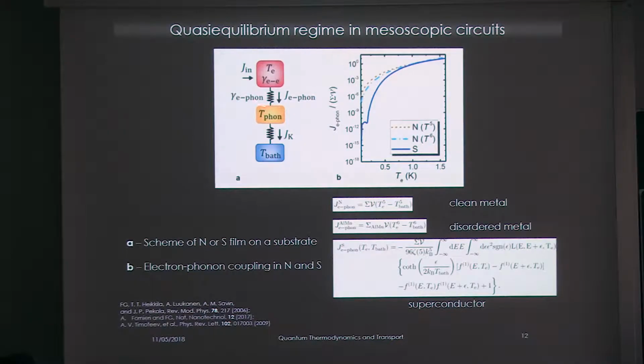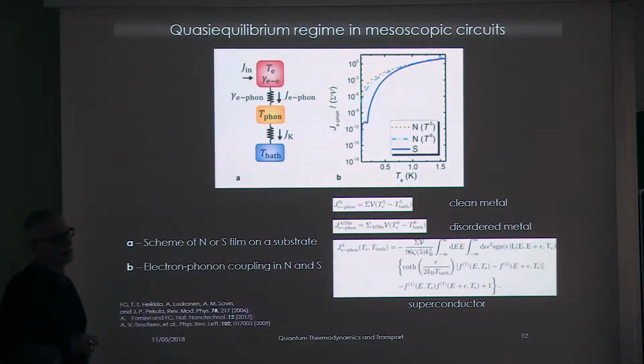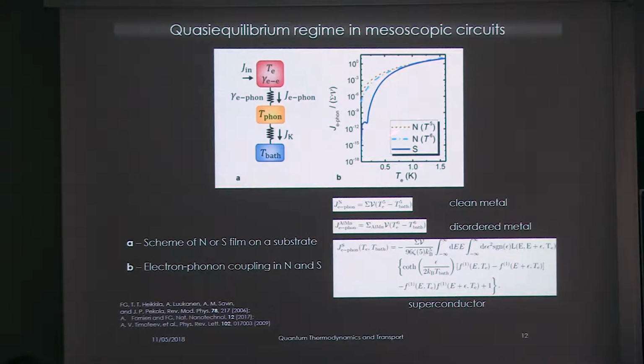If we look at the electron-phonon interaction in metal, this is basically determined by the deformation potential. Whereas in semiconductors, it has a completely different nature. For instance, in III-V alloys like gallium arsenide, indium arsenide, the electron-phonon interaction is determined by piezoelectric coupling. In metals and superconductors, the piezoelectric contribution is very small, so it is due to the deformation potential.